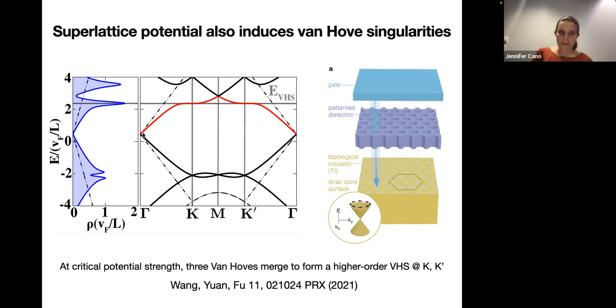But the other thing that happens from having this superlattice potential is that you introduce Van Hove singularities, and these Van Hove singularities are not at the Fermi level, but they're above the Fermi level. So let me say something about this plot. These dashed lines are showing the original Dirac cone with its linear dispersion. Now we apply a superlattice potential, maybe by this method that I was describing with the patterned dielectric, and we get this new band structure, which is the red and black solid lines. And we see that they're not perfectly linear anymore.